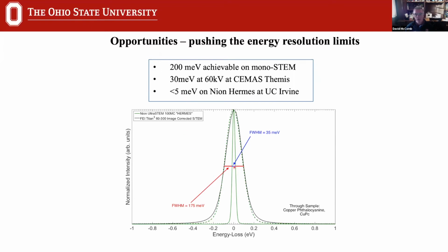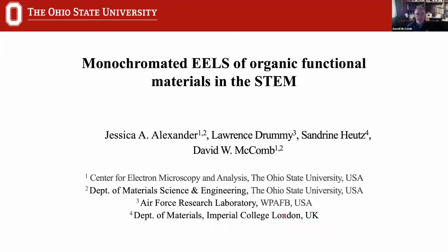And this zero loss peak just illustrates the effects of changing that full width half maximum from of the order of 175 millielectron volts here at the wider spectrum down to 35 and better. And you can see that the big effect of that is that you remove these tails. So you get a much narrower peak, but you lose all these tails, which means that this part of the spectrum now becomes much more accessible. And that's where we're going to start, because we're going to talk about how we can use monochromated EELS, first of all, to study organic materials.